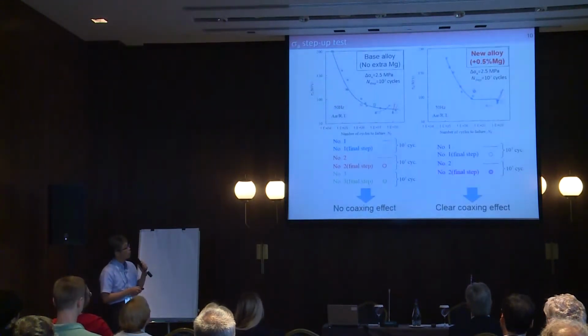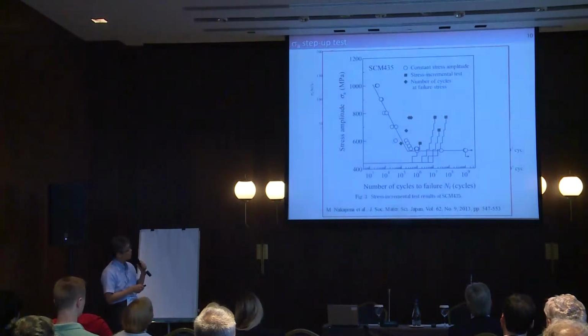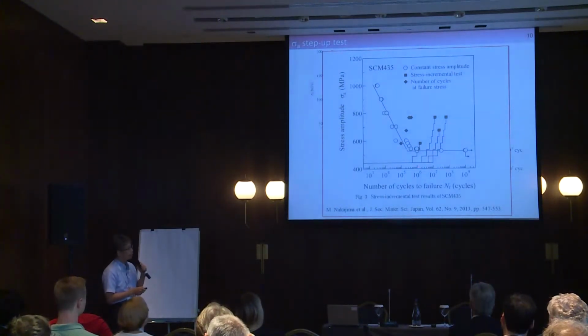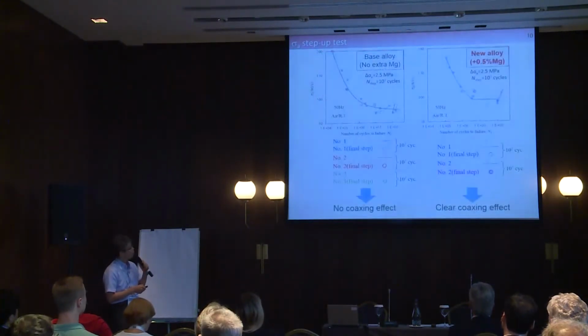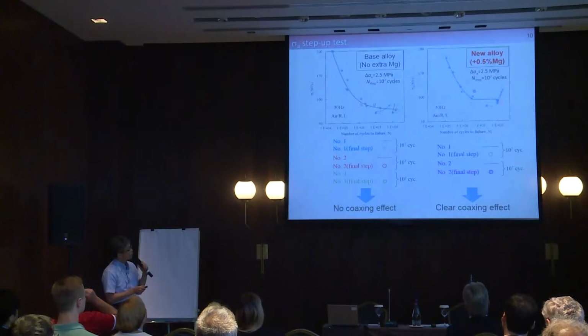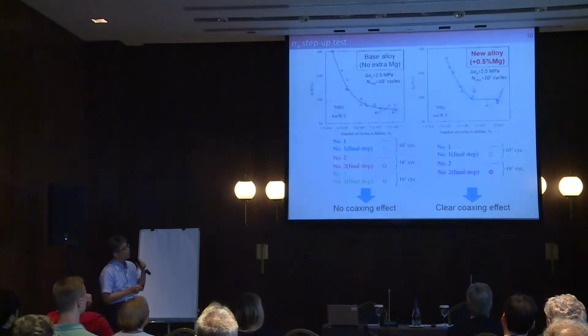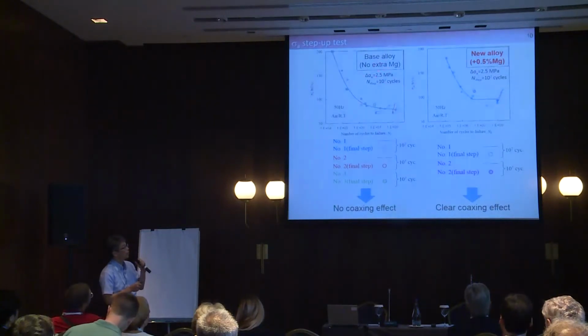And also, we conducted a stress step-up test. If you do a stress step-up test by using conventional steel, the pre-fatigued specimens show much higher strength, which is called a coaxing effect. And what we can see here is that the new alloy clearly shows the coaxing effect because the pre-fatigued specimen is much stronger than the virgin ones. And this characteristic is peculiar to the new alloy, which we can't see in the base alloy.